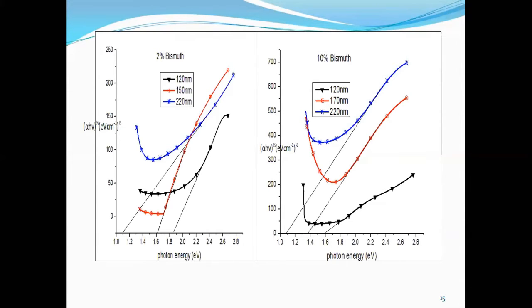Sorry, it is 170, not 150. Sorry, I didn't see that. 170 nanometers. And the black one is representing 120 nanometers thin film. Now, if you look at these two diagrams, it's simply showing that the band gap decreases with increase in film thickness, because you can see the 220 nm for both the graphs. The 220 nm, which is the blue one at the top, is giving us a lower band gap.